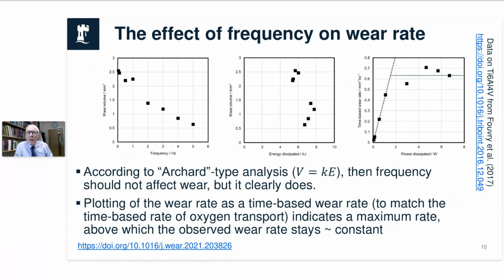If you plot that in an Archard sort of style, that's the middle figure there, the wear volume versus the energy dissipated. The energy was about the same in all of those figures. Not surprising. They were doing exactly the same test except for the frequency. And they saw this stack up of a five-fold difference in the wear volume.